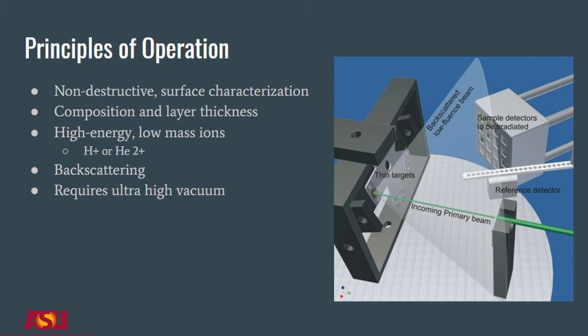It operates on the principle of bombarding a sample with high energy, low mass ions, such as a hydrogen nucleus or a helium alpha particle, and determining the angle at which these ions are backscattered off the sample.